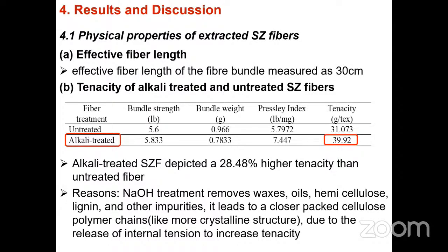The second test we have done for the fibers is tenacity. We have checked the treated and untreated salonica fibers' tenacity, and in this table you can see the treated and untreated fibers' tenacity.